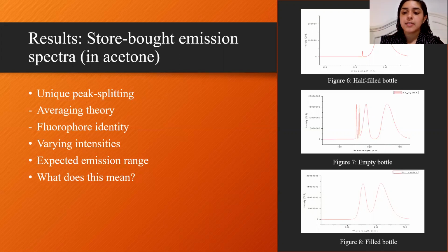As you can see by the spectra in figure 7 and figure 8, there was some sort of a peak separation that occurred. I have personally identified the peak splitting to have been a potential source of the overly saturated sample. However, interestingly enough, the maximum wavelengths at which these peaks are centered actually average out to be a relatively accepted wavelength value for the particular solvent system.